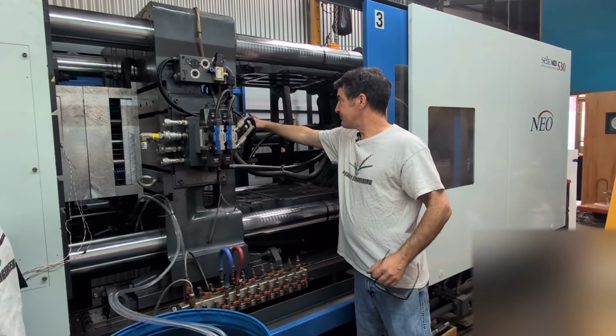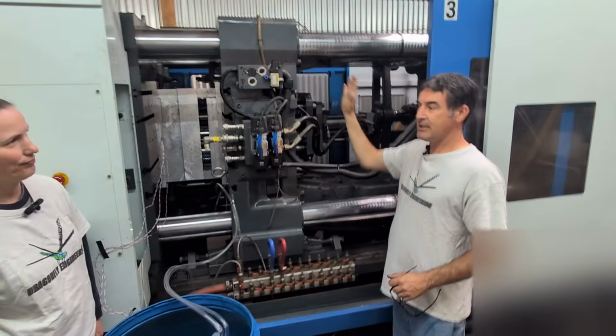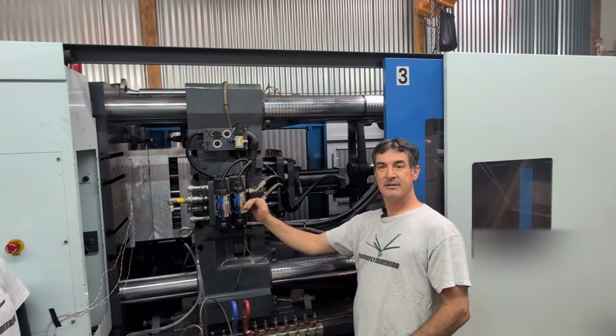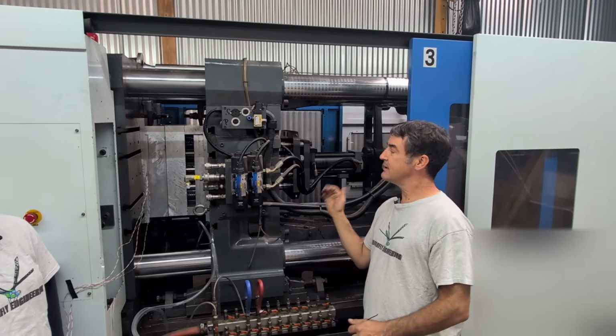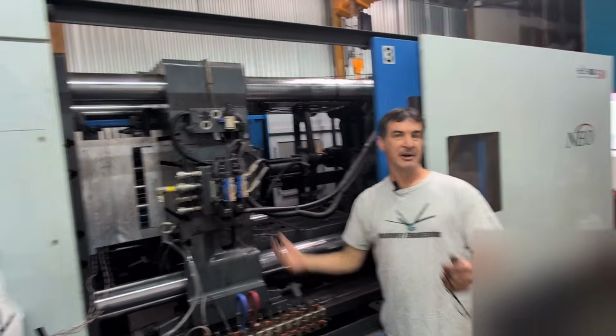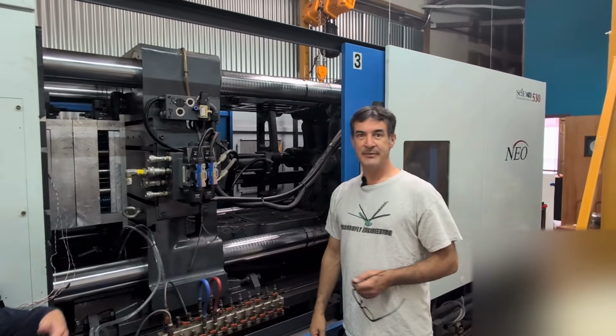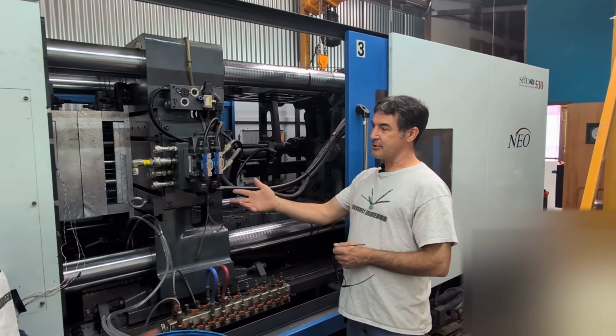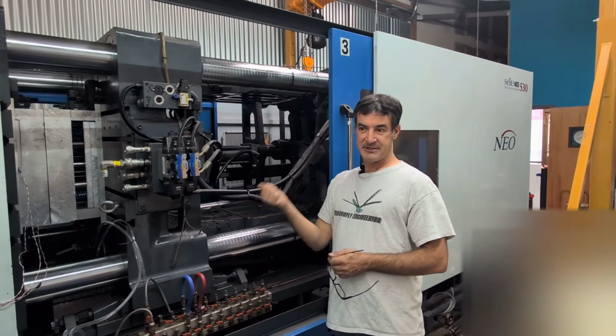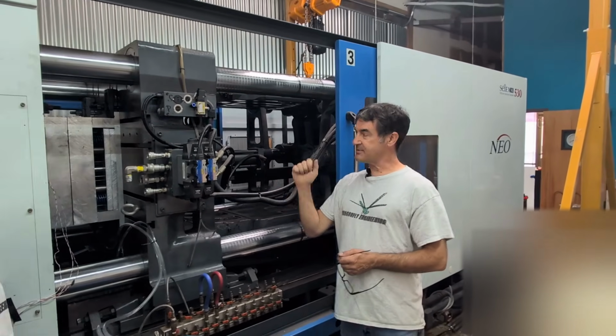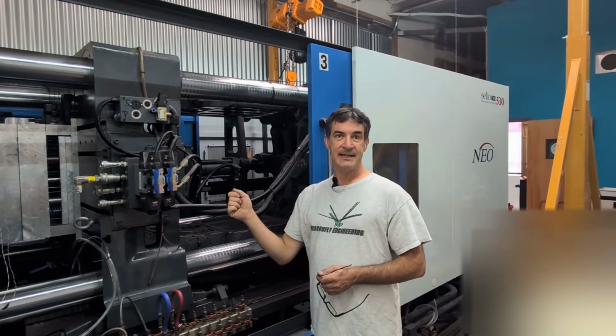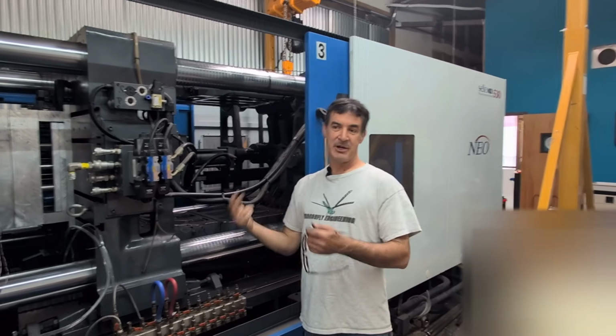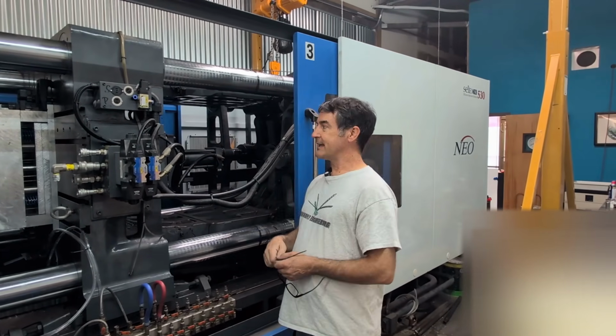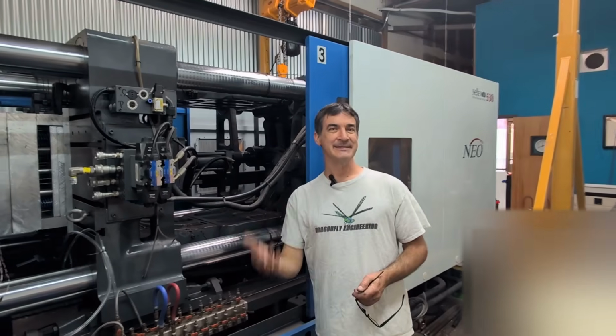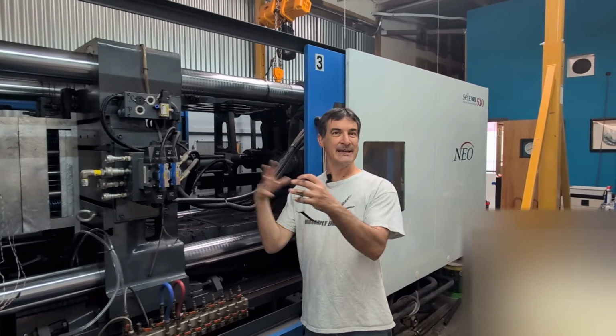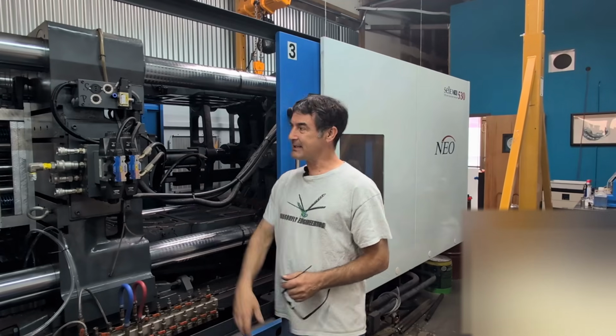And then this ejector system with this hydraulic cylinder will push pins through the mold after the mold half is opened and eject your part out. And then you inspect your part to see what defects you have in it. And then you have to make adjustments to your process parameters with either temperature of the plastic, temperature of the mold, the time it takes to inject the plastic in, the amount of pressure that you're pushing the plastic in, and on and on. And then we'll discuss all these parameters that are interplayed to get a good molded part in your injection molding machine.